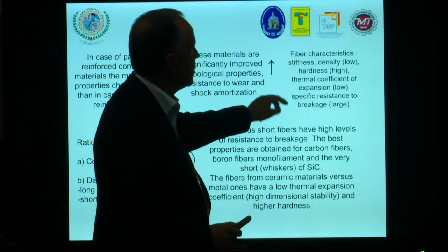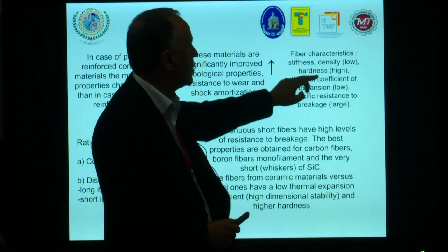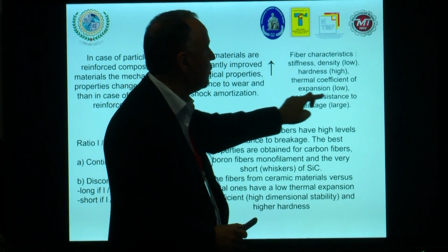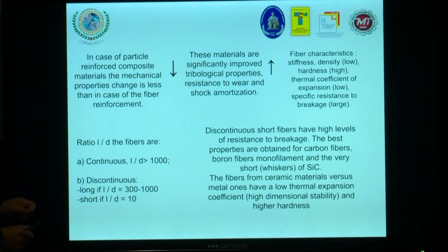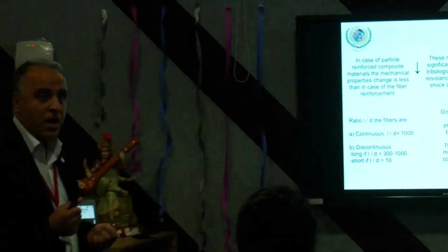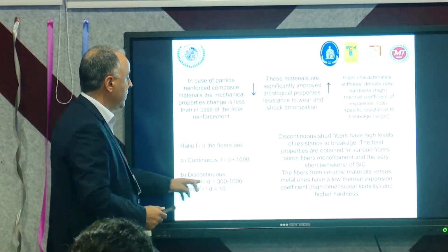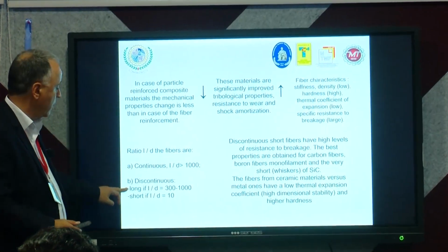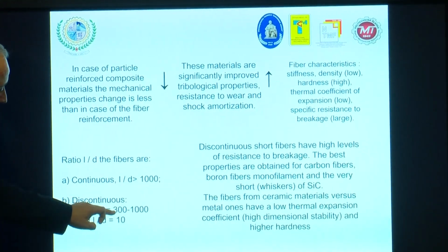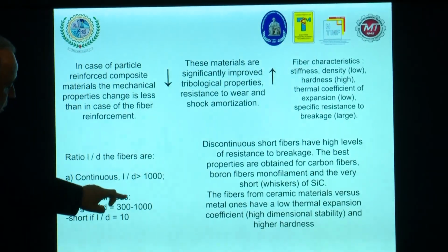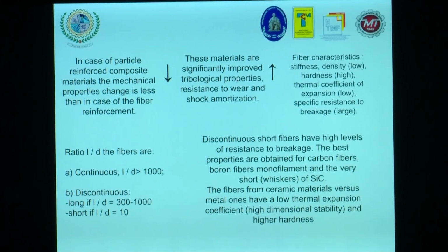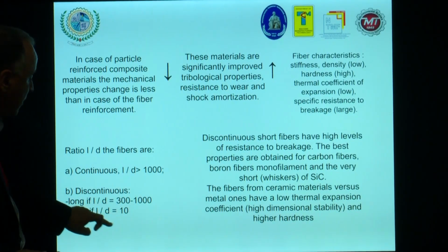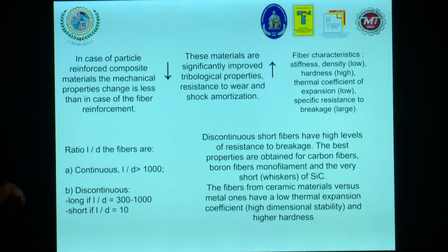Concerning the fiber characteristics, we can talk about the stiffness, density, hardness, thermal coefficient of expansion, specific resistance to breakage, and so on. The fiber has the main rule in order to make a general classification: the ratio between the length and diameter. If this ratio is bigger than 1000, we can call it continuous fiber. If the ratio is between 300 and 1000, we call it long discontinuous fiber. And if the ratio between length and diameter is 10, we call it short discontinuous fiber.